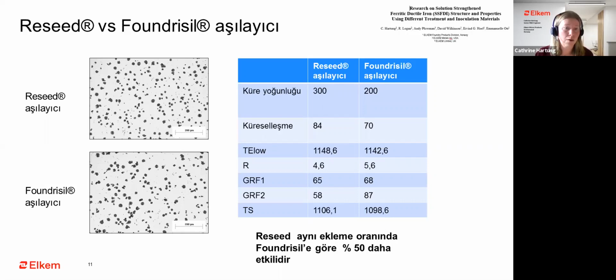So you see a higher TLo, you see a higher TS specifically, and the recalescence is lower. For these SSF irons, the solidification is different than the typical ductile iron, so the graphite factor 1s and 2s are not always as good as you can see with your standard ductile iron. But what you can see here is that the graphite factor 2 is at least lower for the Reseed type. It is not always so easy to use these parameters. But as a result, at the same addition rate in this case, Reseed is providing 50% higher nodule density than Foundrisil, and the nodules are looking a lot better. Next.